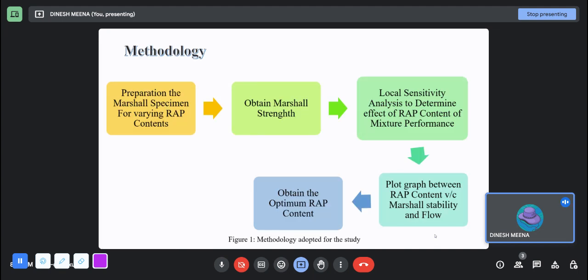Then, the methodology adopted, in which preparation of the Marshall specimen for varying RAP content, obtain Marshall strength, then local sensitivity analysis to determine effect of RAP content on mixture performance. Then plot graph between the recycled asphalt pavement content versus Marshall stability and RAP content versus flow. Then obtain the optimum RAP content.